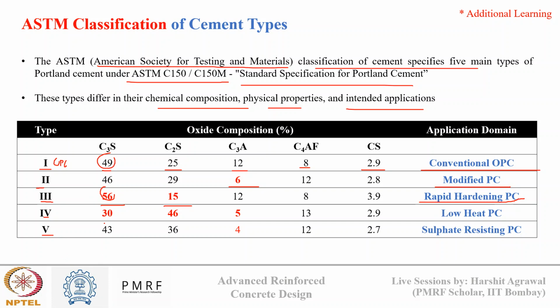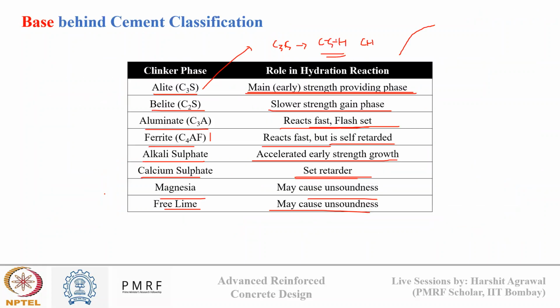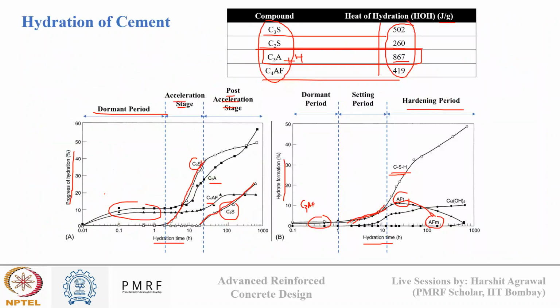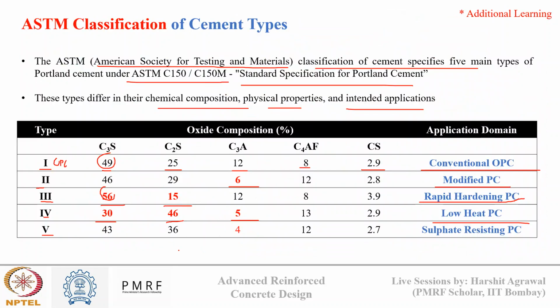Then we have type 4 cement, which compared to type 1, there is a higher proportion of C2S this time and a lower proportion of C3S. So this will be just opposite to type 3, it will be a slow strength gain cement. Okay, since C3S is smaller in quantity and C3A also is smaller in quantity, the heat liberated by this cement also will be lower. So that's why it is known as low heat Portland cement. Okay, we saw in this table, if you remember, amount of heat of hydration in joule per gram. So C3S and C3A have the maximum heat of hydration and C2S has a lower heat of hydration. So since in this type we are reducing C3S and C3A proportion both, this is a low heat Portland cement.